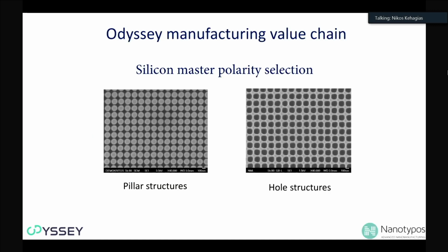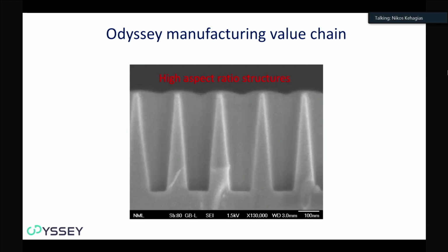As I said, we started trying to find out which polarity had to be fabricated. We started with pillars, and then eventually we saw that that is not the right polarity. So our final process came up with creating silicon molds which had holes. And not only did we have to create the critical dimensions in terms of the diameter, but we had the requirement to also have high aspect ratio structures, to get as high as possible, high aspect ratio silicon hole structures, and maintaining the critical dimensions. And that was not an easy task for us. It was very difficult, even maintaining the tilt angle of these structures. We struggled a lot to achieve our final results.